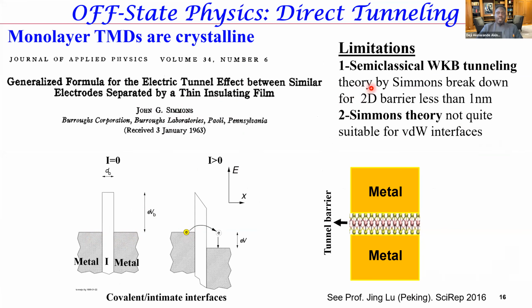The fantastic thing I saw when I first started reading this paper is that John Simmons mentions in the very first paragraph that this theory does not apply for barriers, or it breaks down for barriers less than 1 nanometer. So if you have an insulating barrier less than 1 nanometer, the theory begins to collapse because this WKB, or this triangulation of the barrier, collapses—you're neglecting dielectric constant effects, you're neglecting image force correction effects. All these effects that don't play a role if the barrier is thick become very dominant when the barrier is less than 1 nanometer. So that is one reason we could identify.